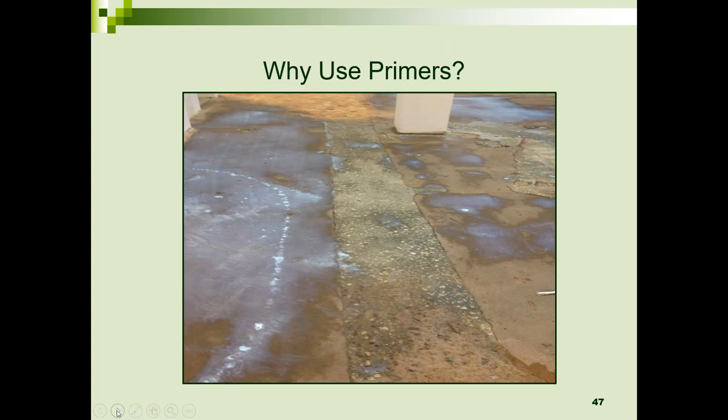If you have a trench in the substrate, again, pay attention to priming. A trench is done for utilities. The trench is generally a different mix design, with different finished or cured qualities than the adjacent concrete. So it may be more porous than the concrete on either side. So pay attention when you put a primer down, you want to see a distinct film. If you have a very absorbent surface, you may need to apply the primer, first application diluted 3:1, followed by multiple applications until you get a distinct film on the surface. So again, primer application may require more than one step prior to a tile or an underlayment installation.